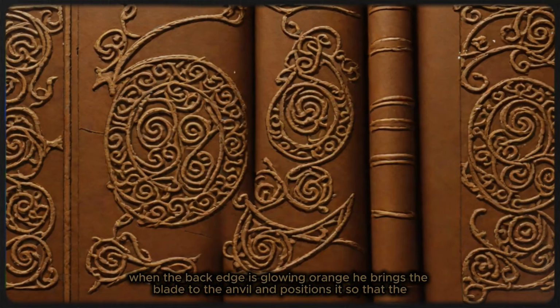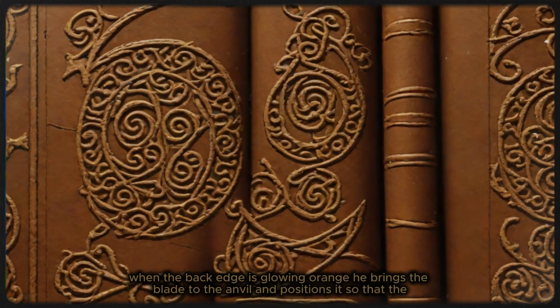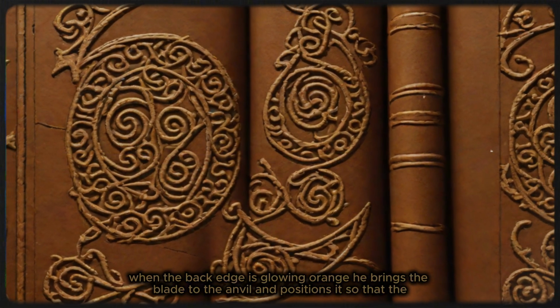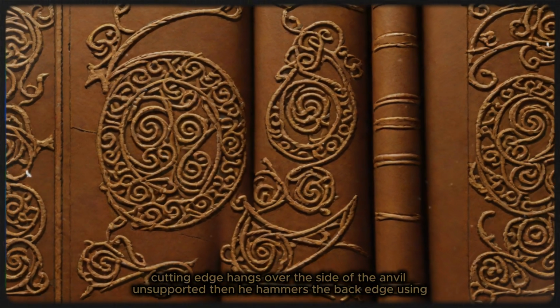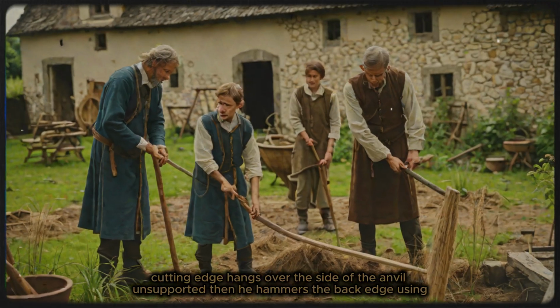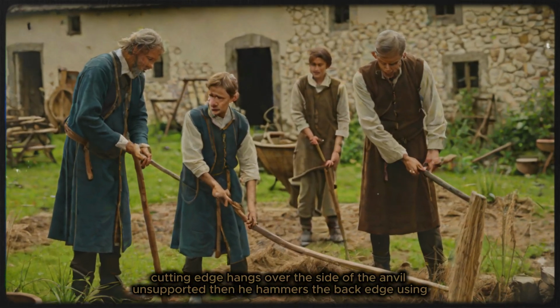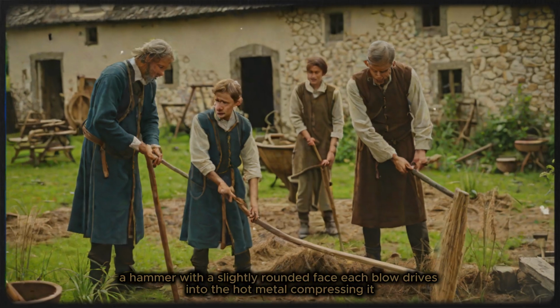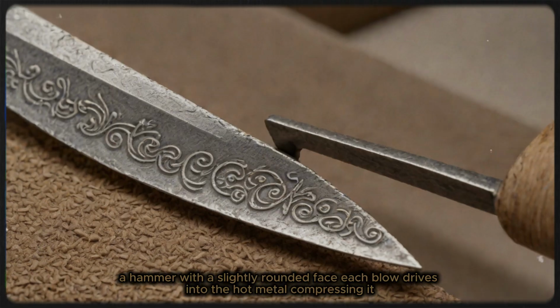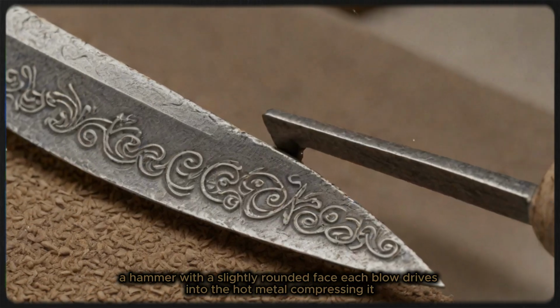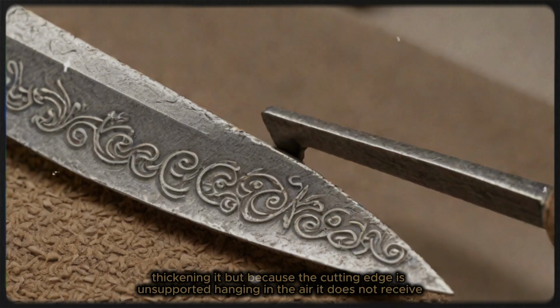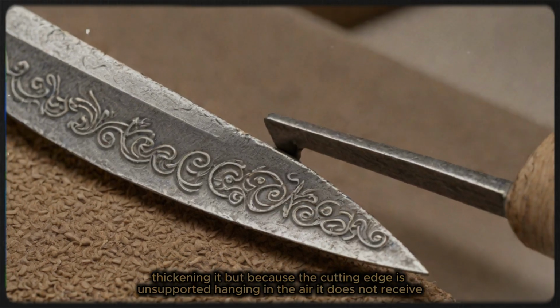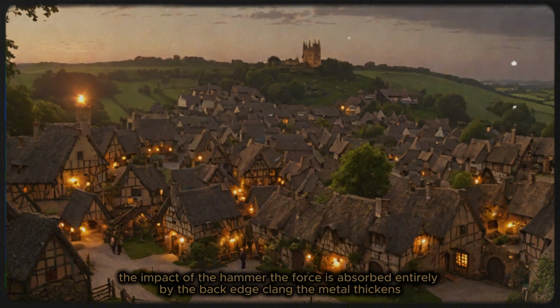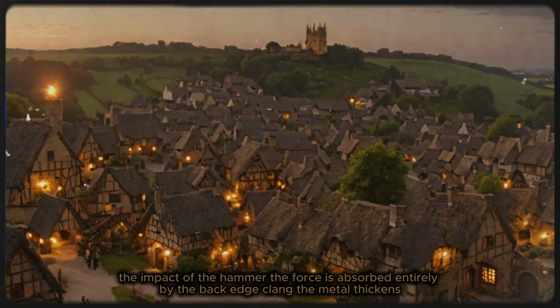When the back edge is glowing orange, he brings the blade to the anvil and positions it so that the cutting edge hangs over the side of the anvil, unsupported. Then he hammers the back edge, using a hammer with a slightly rounded face. Each blow drives into the hot metal, compressing it, thickening it. But because the cutting edge is unsupported, hanging in the air, it does not receive the impact of the hammer. The force is absorbed entirely by the back edge.